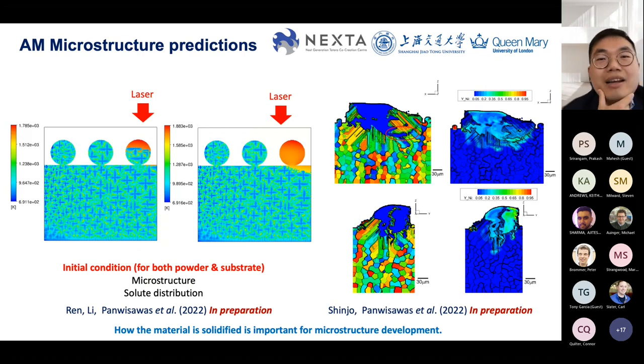So in order to actually understand the role, again, not just of the thermal chemical fluid, but also link this one to the solute field, which actually happened in the solid state of the material, we are now investigating the role of the interaction of the laser and the powder as a function of the chemistry. Then we can elucidate some phenomenon like solute trapping or rapid solidification that leads to non-equilibrium microstructure. This work is quite important because in order to understand how materials solidify, it's important for microstructure and property scatter in the process. And for example, if we use in-situ alloying, how can we understand what is the solidification pathway for that system? And that's what we are developing, a mathematical framework to do that.